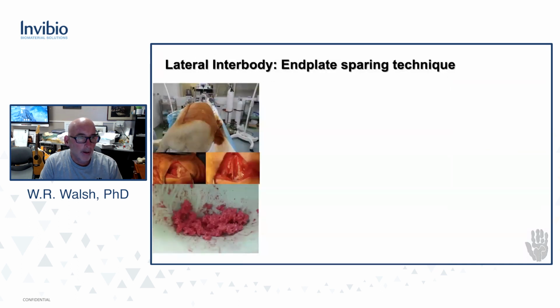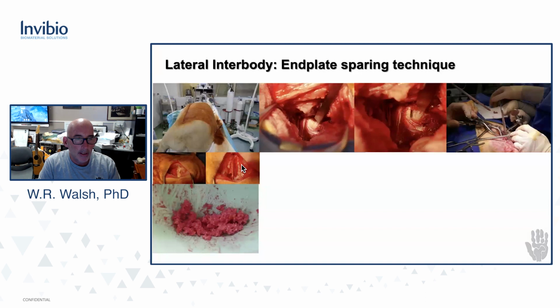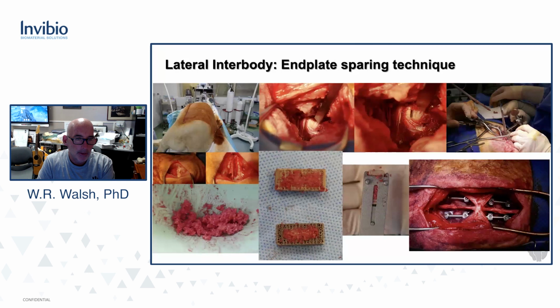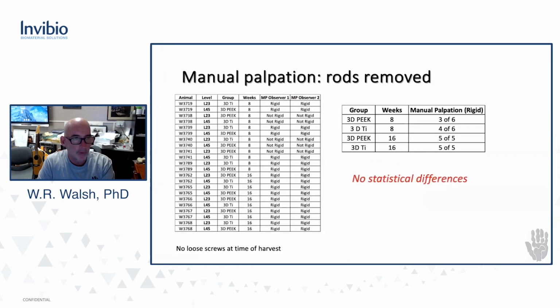And if we look at our animal model, it's a lateral approach, expose the disc, this is harvesting the autograft off the iliac wing, and then expose the disc, do an annulotomy, nucleotomy, prepare the end plates, crack the spine open with Caspar pins, put the graft in your cage, put it in and insert it so that the graft does not fall out, and then insert it, flip it over, put pedicle screws in.